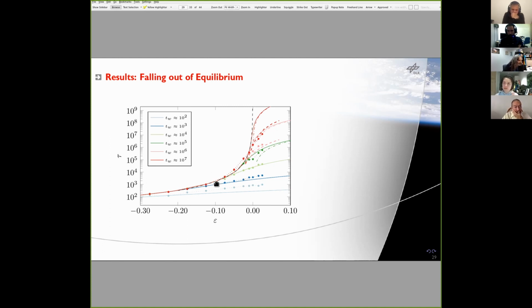Just for completeness, I also show you the other plot that I also had in the beginning, where we fix the waiting time, and then we look at the relaxation time as a function of the density to which we quench, which I now represent as a distance parameter. So quenching to the critical density would be epsilon equals 0. Quenching into the glass would be epsilon larger than 0. And again, you see computer simulation and schematic model, and the lines more or less go through the data points,